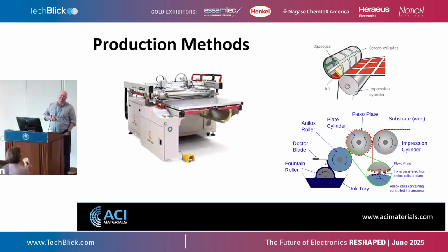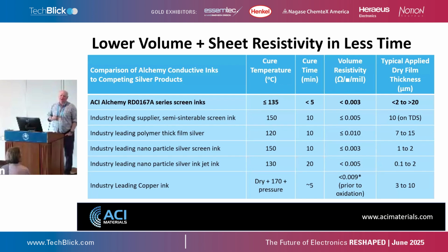Now, really, I've spent a lot of my time not just in materials, but in manufacturing. I was 10 years in roll-to-roll and sheet-fed manufacturing of print electronics. There are various production methods, but still predominantly our industry, for low, medium, and high volume, is sheet-fed screen printing. But we're also edging now with these materials into roll-to-roll screen and flexo printing for high definition. But what's most important is not printing at high speed, it's drying and performance at high speed with a wide process window for depositing very thin to very thick.